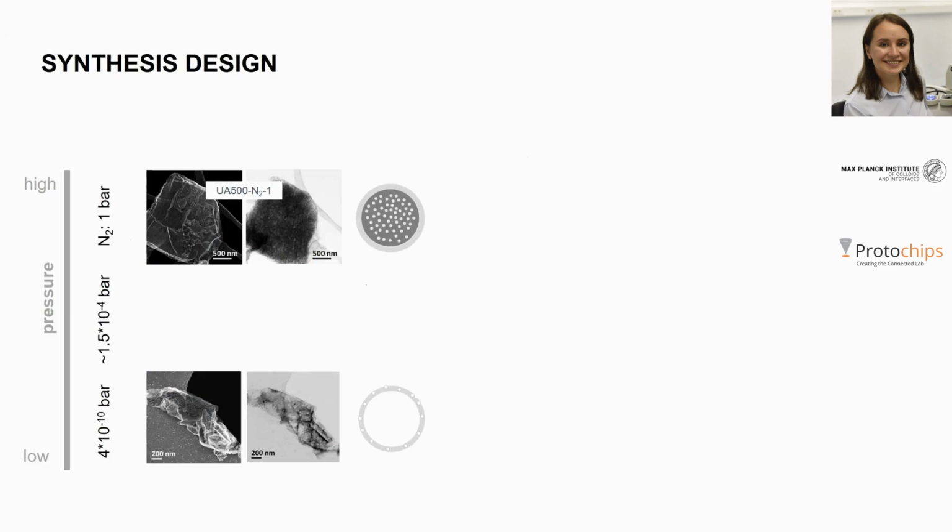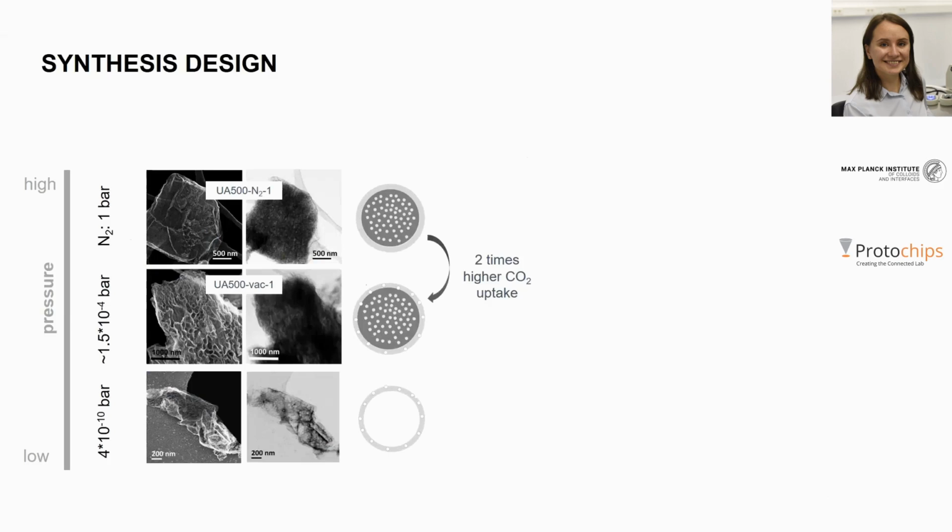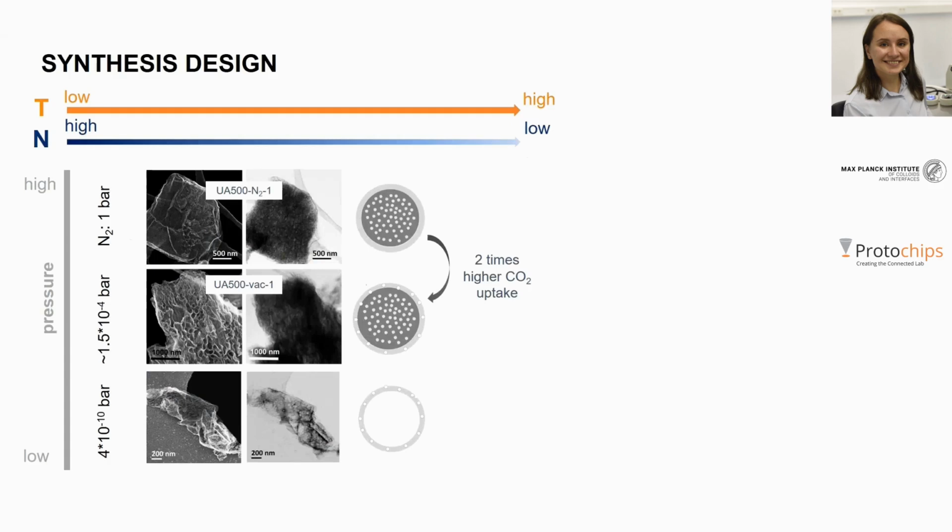Not only high CO2 uptake, but also high selectivity of CO2 capture and strength of binding are crucial to obtain superior CO2 adsorbents. We found that selectivity can be improved by using high heating rates. In our case, it's 10 degrees per minute. And also that the strength of binding for the sample synthesized in vacuum is much higher.